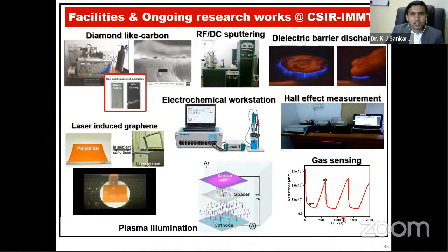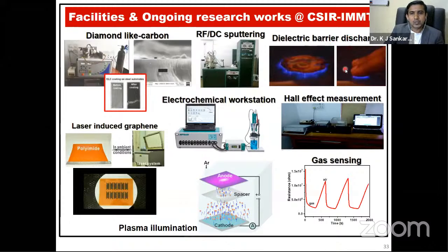So these are the facilities and ongoing research work that I'm carrying out in CSIR IMMT for the last 1 year. So we have a system to grow diamond-like carbon, also diamond films, with a microwave plasma CVD. And this is the RF and DC sputtering system. We can grow metal oxide thin films. And recently we carried out work with dielectric barrier discharge, where we can do some oxygen plasma treatment on any kind of material to change it from hydrophobic to hydrophilic nature.